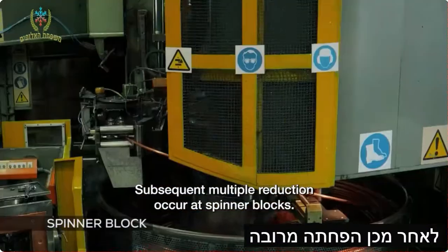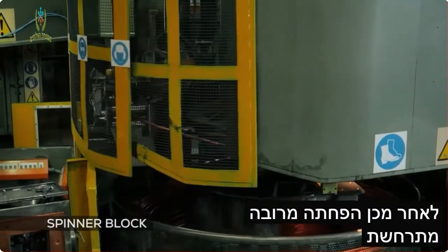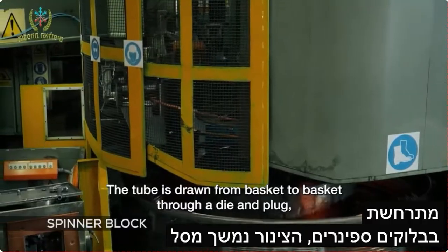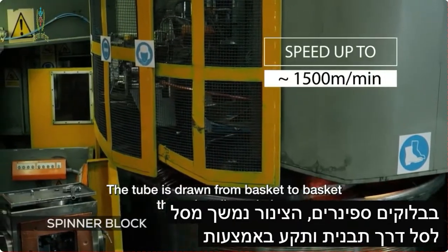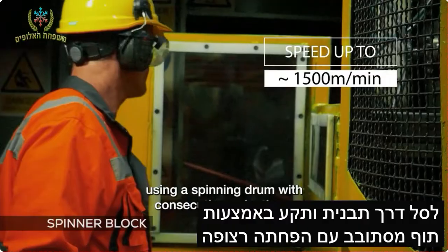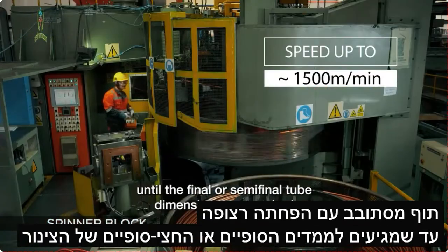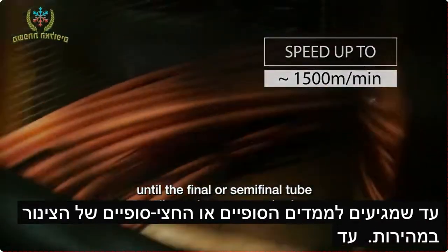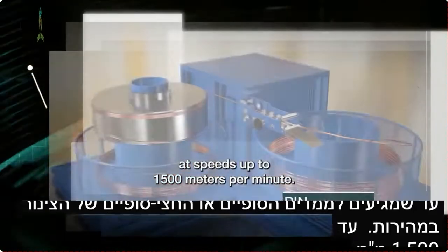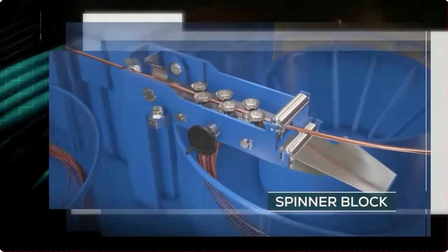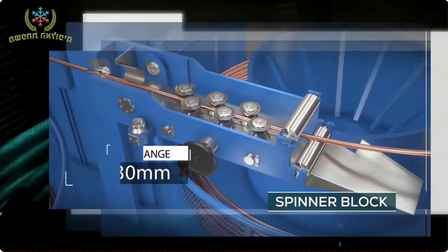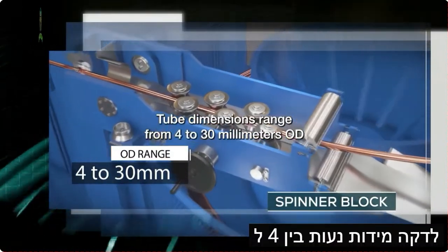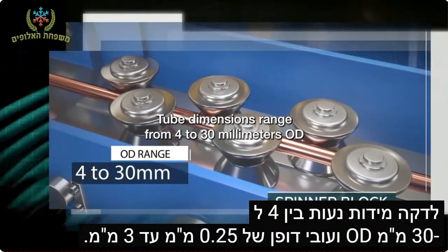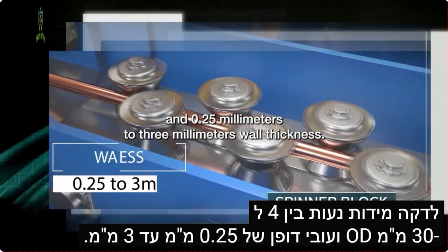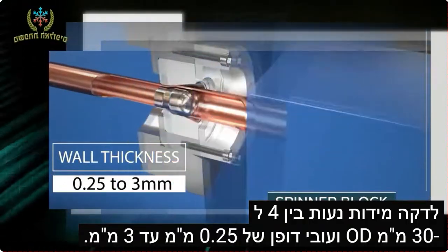Subsequent multiple reductions occur at spinner blocks. The tube is drawn from basket to basket through a die and plug, using a spinning drum with consecutive reductions, until the final or semi-final tube dimensions are reached at speeds up to 1,500 meters per minute. Tube dimensions range from 4 to 30 mm OD and 0.25 mm to 3 mm wall thickness.